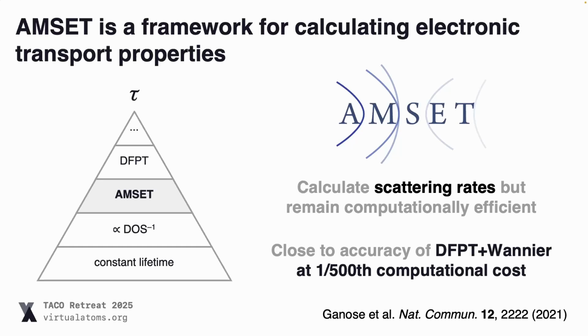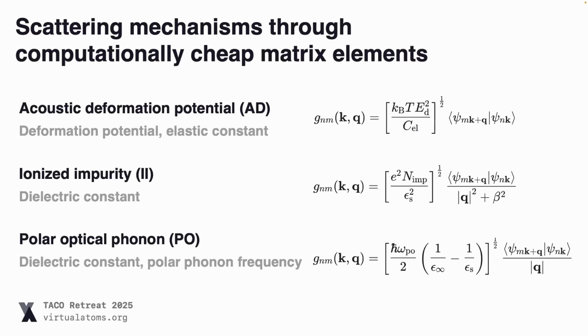On the other side of the spectrum, you have methods based on density functional perturbation theory, often combined with Wannier interpolation. And these are very accurate methods for obtaining electronic transport. The issue is that they're extremely expensive. And so what we wanted to do was kind of bridge this gap and develop a method which was close to the accuracy of density functional perturbation theory, but at a computational cost much closer to these constant lifetime and cheaper approaches. And so happy to say that we did that. So our method AMSET essentially allows us to explicitly obtain the scattering rates whilst remaining computationally efficient.